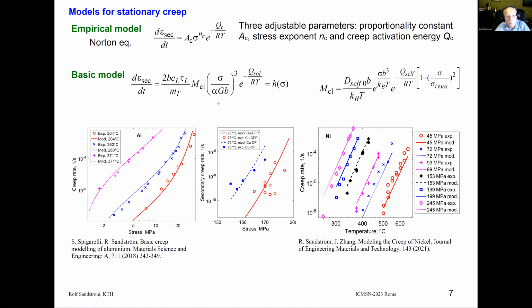It's also possible to derive this equation, and here is the result. This can be obtained more or less directly from the basic dislocation equation, and all the parameters here are well defined. Most important part is probably the climb mobility, and this has been derived in the literature, so that it's completely well defined.